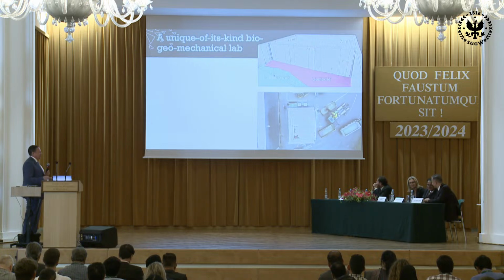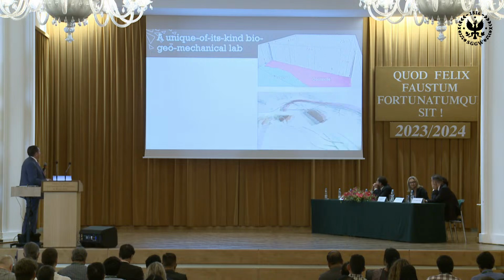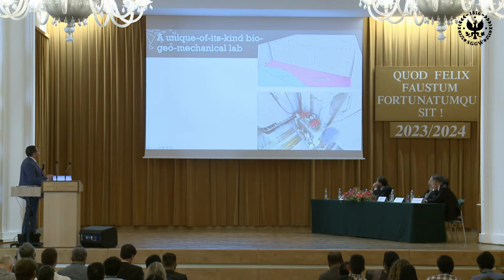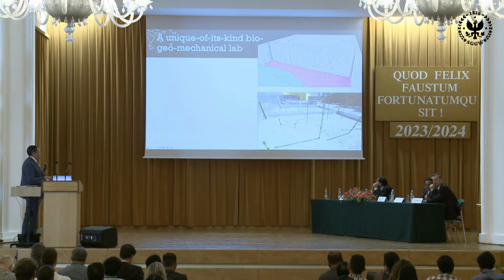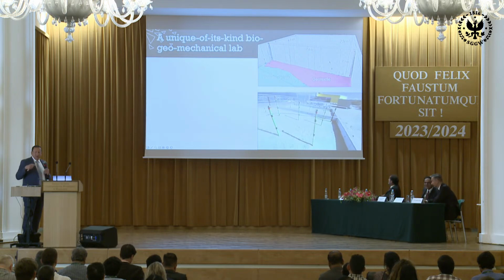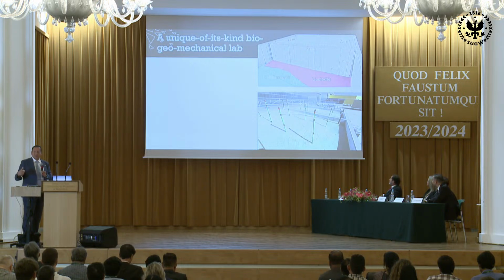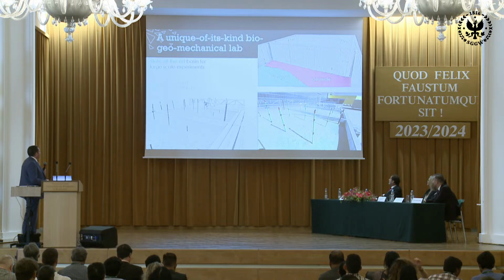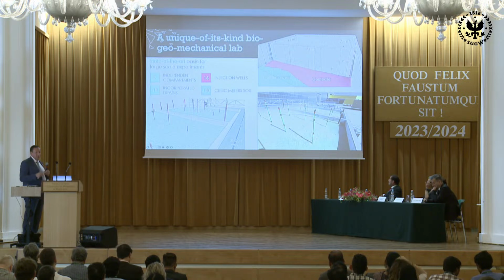So to validate such a numerical or theoretical approach, we constructed a unique-of-its-kind worldwide facility to test the behavior of the material in almost similar conditions as in reality, in situ. So what we have are 2 compartments. Each time we try to have one where the material is untreated, so we do not inject anything, as a reference case. And then a second compartment that is treated.